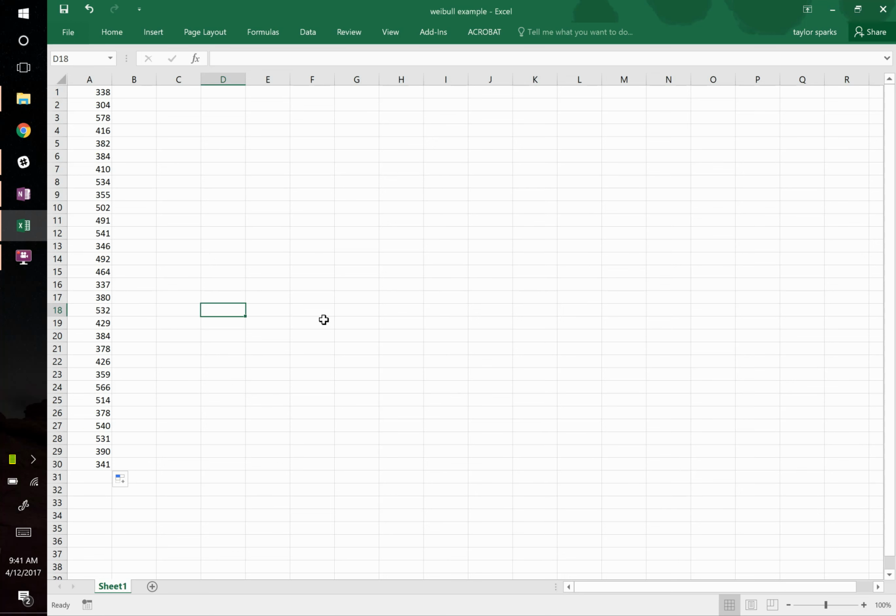Weibull works really well when you've already got a process and it's small changes. If you're doing a big change, like if your bars have major defects in them and you're trying to do a Weibull analysis, the flaw range is so big it's hard, because you've got different types of flaws. You've got delamination versus the pores inside. This is good for fixing one type of flaw at a time.